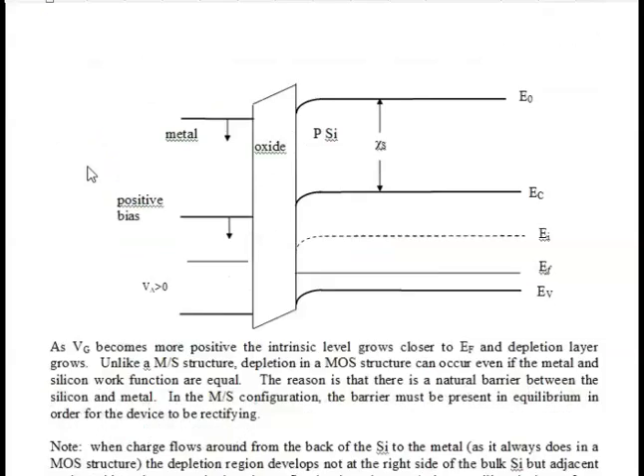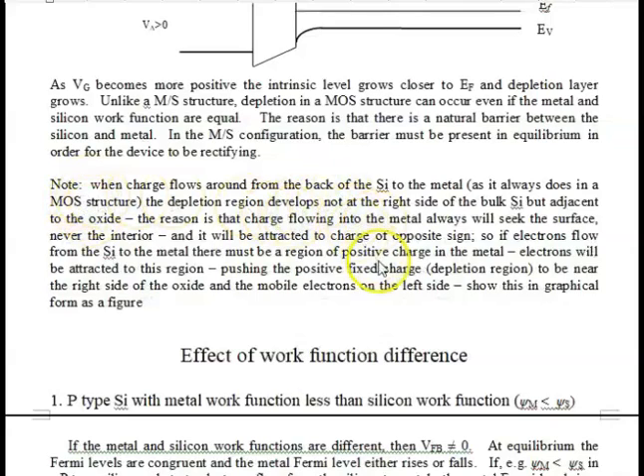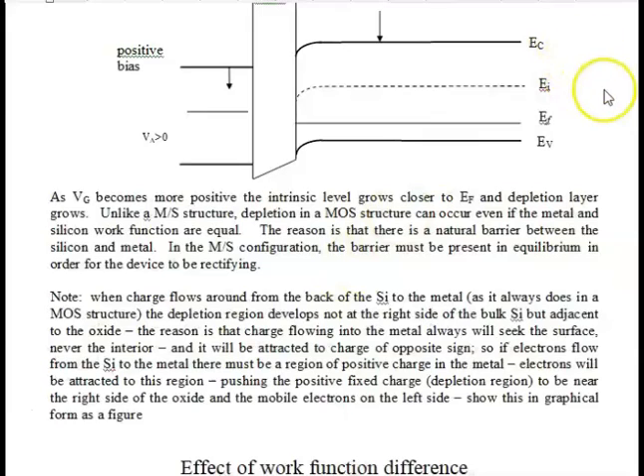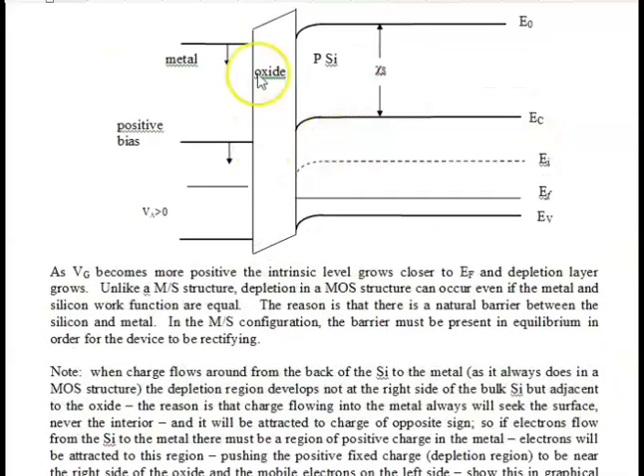Okay, let's trudge on. There's just a little note here that really we have a connection between the back end of the silicon and the metal, and charge always flows from the back end to the metal or vice versa. But this is where the action takes place, because this is where the charge accumulates. So if I have positive charge at the metal oxide interface, I'm going to pull over negative charge from the oxide silicon interface. So this is where all the charge occurs. There's no fixed charge or even mobile charge here. This is all quasi-neutral, and here, of course, since it's a metal, it is certainly neutral.